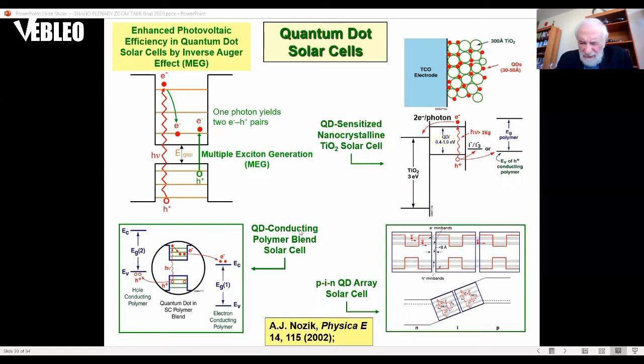So in terms of quantum dot solar cells, there are several ways to utilize the quantum dots in the solar cell. One is to just have an array of quantum dots and put them onto a supporting material like titanium dioxide, a wide bandgap semiconductor, and then you create multiple electrons per photon and transfer them into the supporting TiO2 substrate, and then collect the electrons on one electrode, and the holes will be collected on the second electrode.